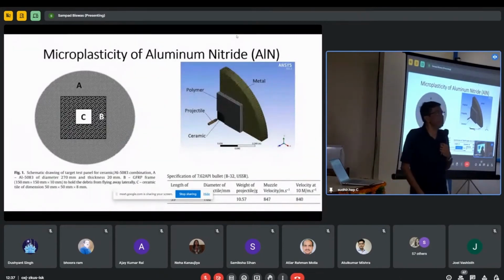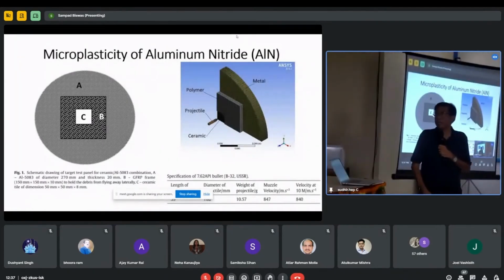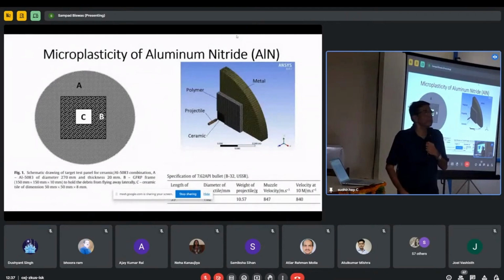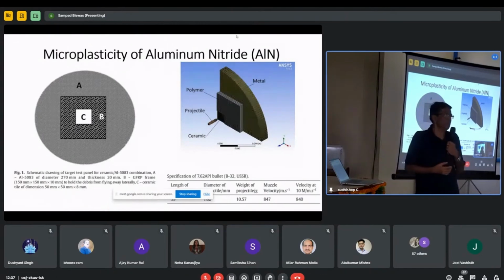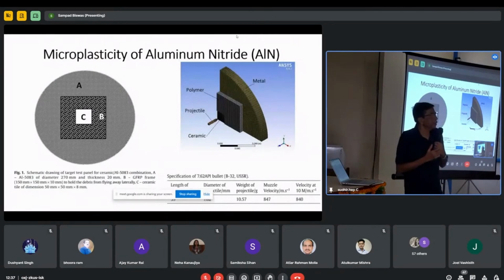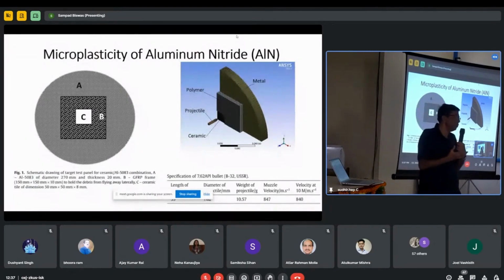See, aluminum nitride is a wurtzite, hexagonal crystalline lattice, and it has very interesting properties. If you apply a confinement load in aluminum nitride ceramics, what will you get? You will get a transition of the properties from brittle to ductile.